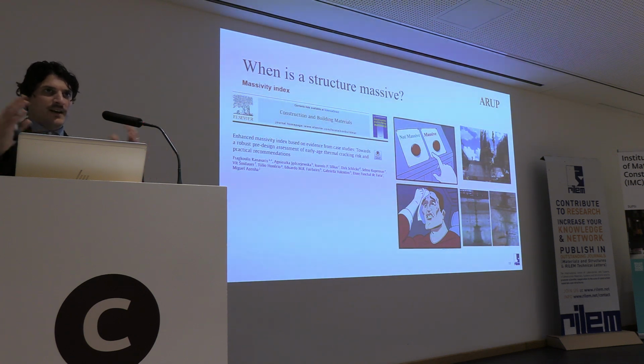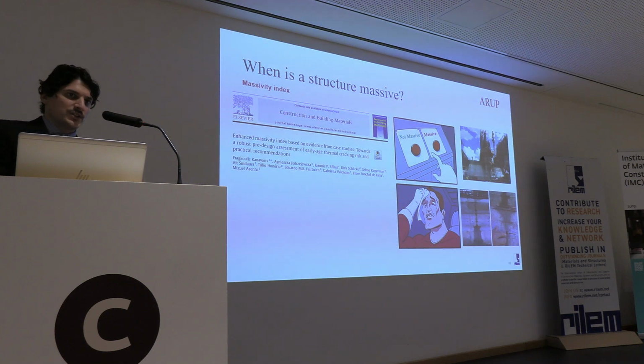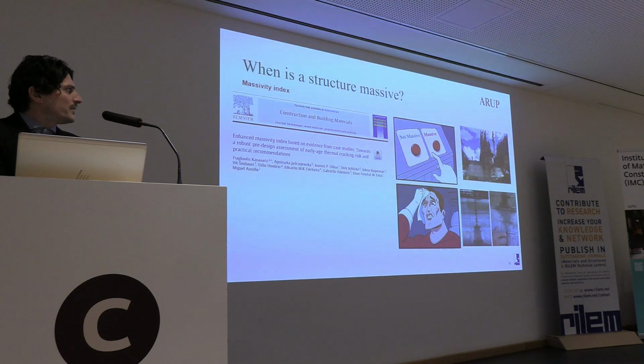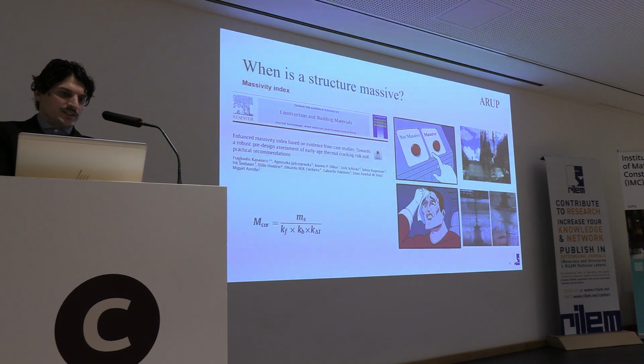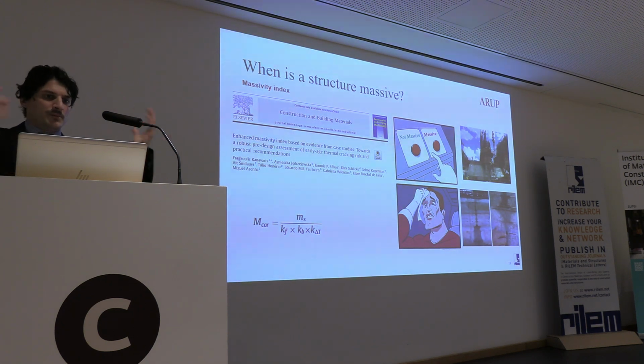For example, there is a big kind of dilemma out there in the industry as to when a structure is massive or not massive, because if it's being classified as massive, there could be implications with developing additional reports, thermal control plans. There could be liabilities involved, and so on. And for not massive structures, it's kind of more easy life. You don't have to worry about cracking and so on. But there was not an evidence-based approach that could predict this type of cracking effects as the one in this massive spillway somewhere that I shouldn't be saying where that is. So we developed, through an interdisciplinary study and evidence-based approach, a kind of simplified manner to assess the massive concrete cracking risk. And by saying that, massive concrete mainly is a problem of volume. You got a big volume, but it's not just volume.